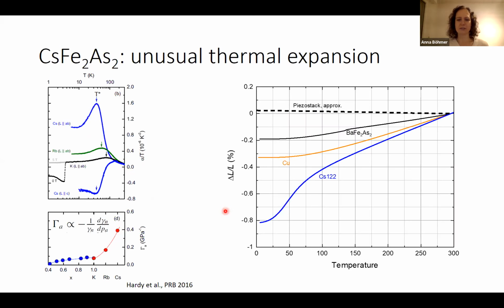I can plot not the alpha, the thermal expansion coefficient, over temperature here. I can also plot simply the length change. What we see in the cesium 1-2-2 is that it shrinks a lot on cooling. It shrinks more than twice as much as copper metal, 4 times as much as barium 1-2-2, and very different from a piezo stack. So a sample on a piezo stack would already experience a huge amount of isotropic strain. So we thought it might not be the best idea.